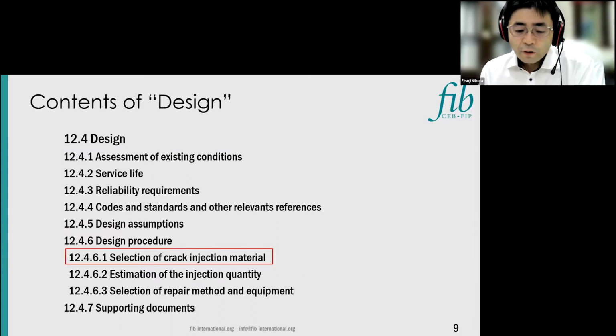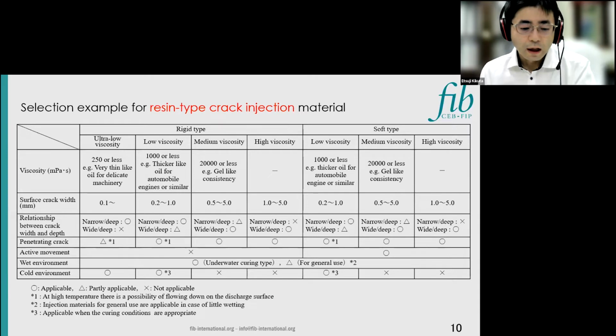About design, here I will cover selection of injection materials. At first, about resin type materials, there are a rigid type and a soft type in the resin type materials, and each type has materials with various viscosities. A material with an appropriate viscosity must be selected according to the crack width, environmental temperature, and other execution environments. Generally, the rigid type is less expensive, but the rigid type does not have flexibility. So it is not applicable when the cracks have opening and closing behavior. The soft type is applicable to such cracks.